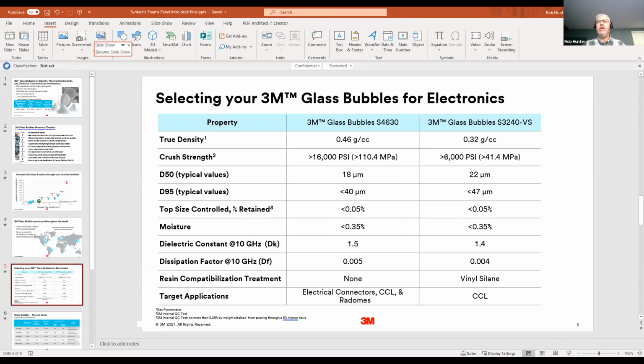Yep, so the two new products, just real briefly. The main differentiator is we're warranting a tiny fraction of top size. That's the main thing. I'm not a 5G or semiconductor expert. This is new territory for me, but we have heard loud and clear that large particles are detrimental to many applications. And so we take pains to eliminate the top size fraction. So we're warranting by our new test 0.05% by weight retained top size particles over a 53 micron equivalent mesh size. That's the principal thing.